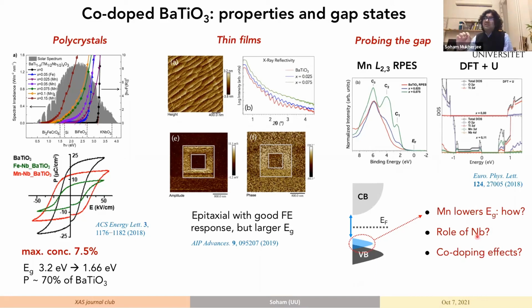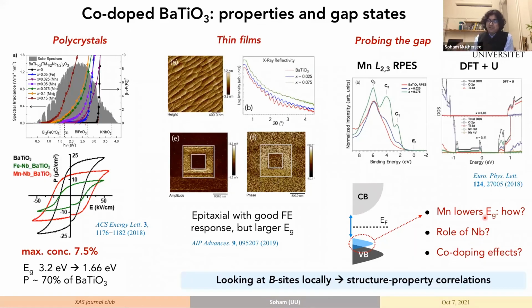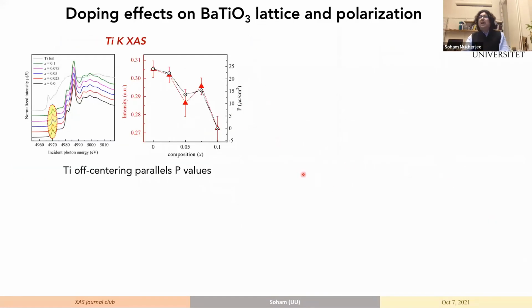But we got interested in looking at the niobium and what niobium is essentially doing to the system, and what co-doping together, both manganese and niobium, does to the system. And with this, we went ahead and performed titanium K-edge XAS, and we see the nice pre-edge feature, which leads to the quadrupolar transition and a bit of dipolar transition as well. But this relates to the titanium off-centering, and we do see that there is a systematic decrease with doping, which means that the total ferroelectricity of the system is going down with some glitch at the 7.5 sample.